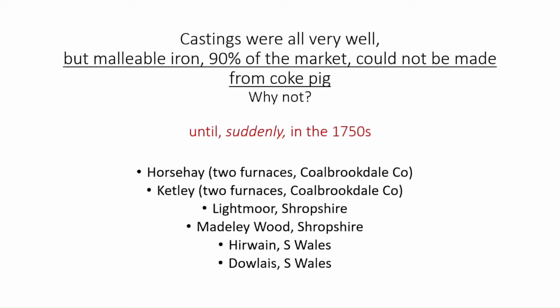Okay, so I'm going to move off castings. For the first 50 years, you couldn't make malleable iron with the pigs that came out of the coke-fired blast furnace. Why not? Well, it was because inevitably you had sulfur present in the iron that came from anywhere near a piece of coke or coal. You reduced the sulfur content of coal when you coked it, but you still had sulfur left, and if it came in contact with the iron, it would pick it up.